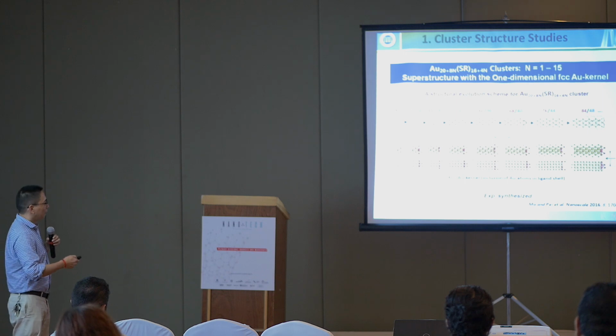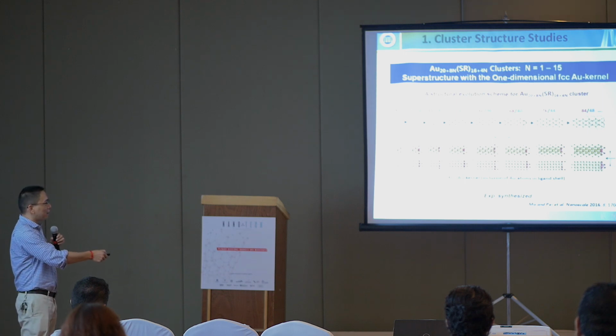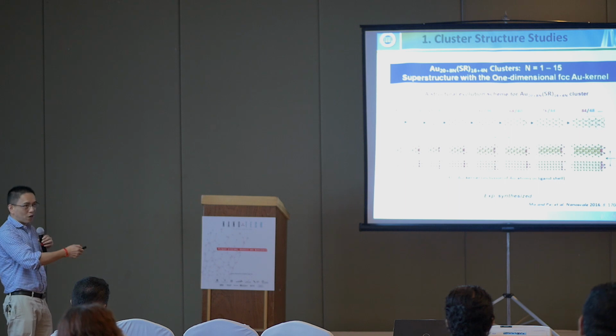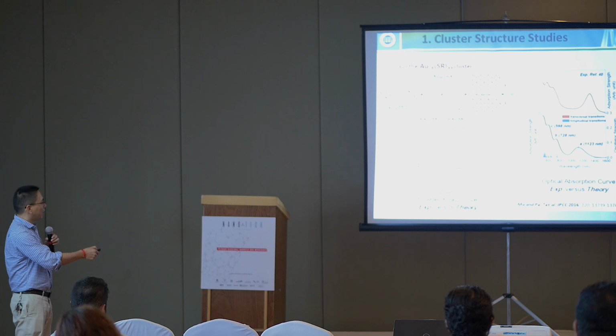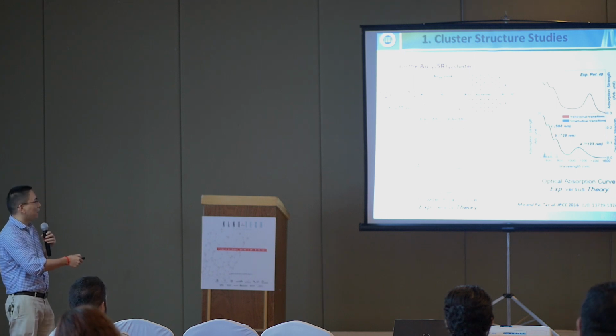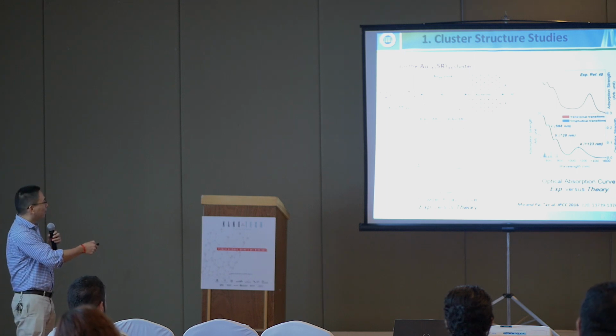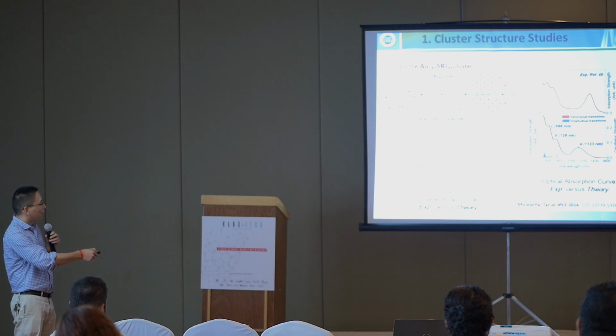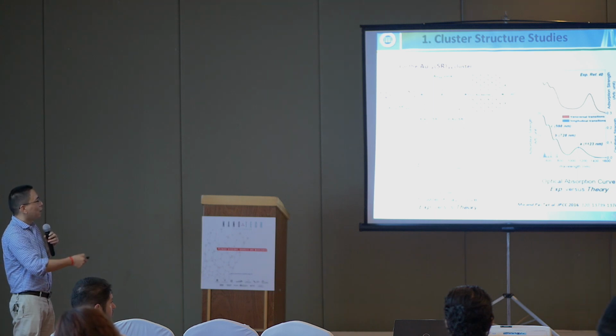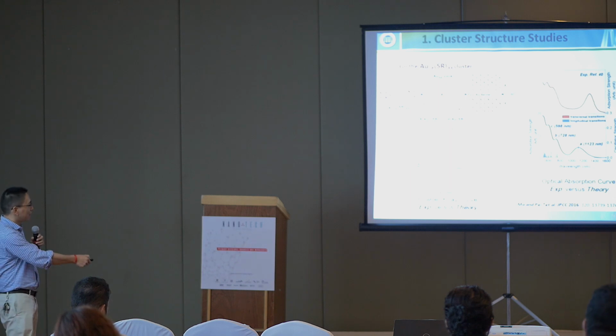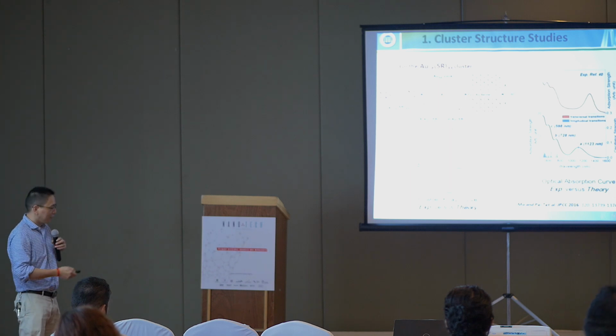So we can easily obtain its cluster structure from theory. Then we carried out theoretical calculations. Here is the structure model, and the right one is a comparison of the experimental optical curve and the TDDFT results here. We can see the features, the peaks here and here, all agree very well with the experimental curves. Okay.